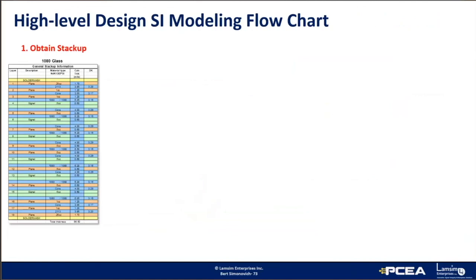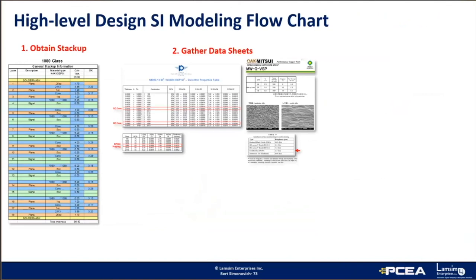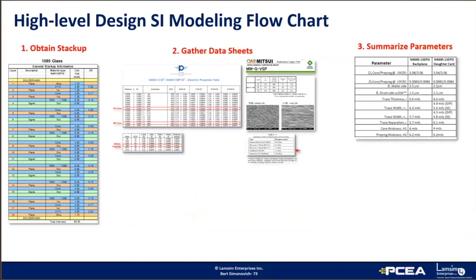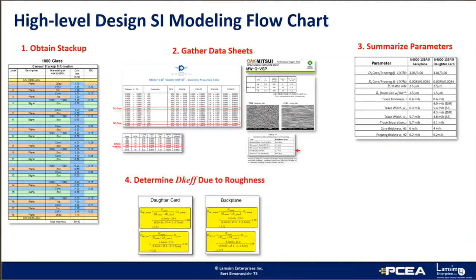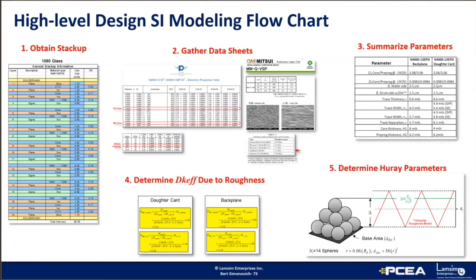The first thing to do is get the stack up from the board shop. Next, gather up the necessary data sheets from the materials for the dielectric we use in the DK, DF tables. Then it's useful to summarize all the parameters into a table. After that, determine the effective Dk due to the roughness using my Dk effective correction model. And lastly, determine the Huray parameters of the matte and the drum side using my cannonball stack model.